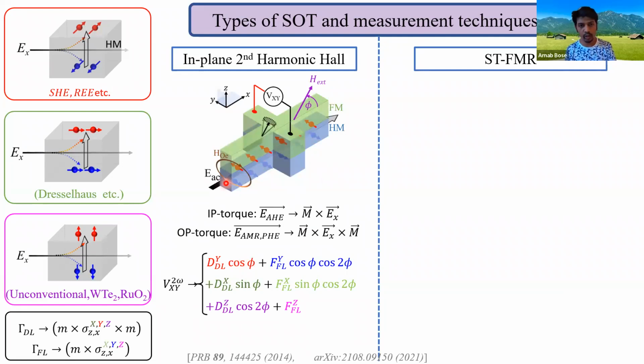If we have field-like torques, out-of-plane field-like torques from the standard Oersted field or Rashba-Edelstein effect, then the angular dependence would be cos phi, cos 2 phi. For example, if you have out-of-plane spins, and if that produces damping-like torque, meaning out-of-plane damping-like torque, then we'll have angular dependence of cos 2 phi, and so on and so forth. So the bottom line is, by fitting the experimentally measured second harmonic Hall voltage with these expressions, we can identify and quantify all different types of torques.